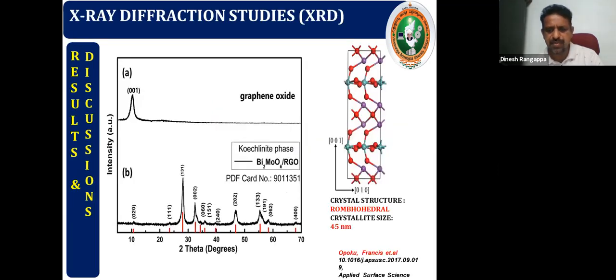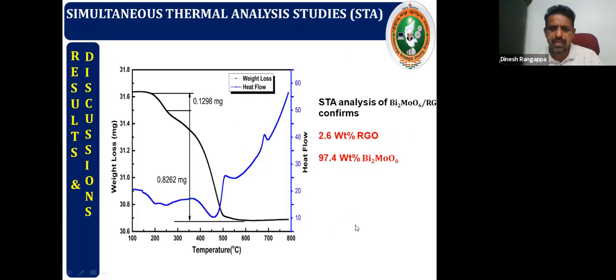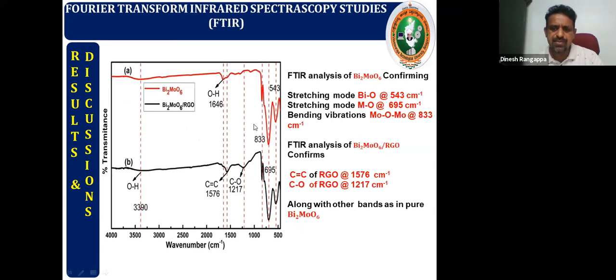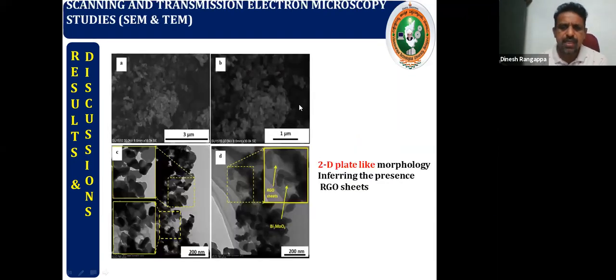So here you can see the crystal structure of bismuth molybdate and RGO nanocomposite, and it shows a rhombohedral structure with a crystallite size of about 45 nanometer. And the TGDTA shows the presence of only 2.6 weight% of RGO in this nanocomposite. And FTIR shows the presence of RGO, meaning carbon on the surface, and also bonding between molybdenum and oxygen. So here the SEM and TEM images show the two-dimensional plate-like morphology, plate on sheet kind of morphology we can see here. In the background there is a graphene sheet, and bismuth molybdate plates are being coated on the RGO sheet.